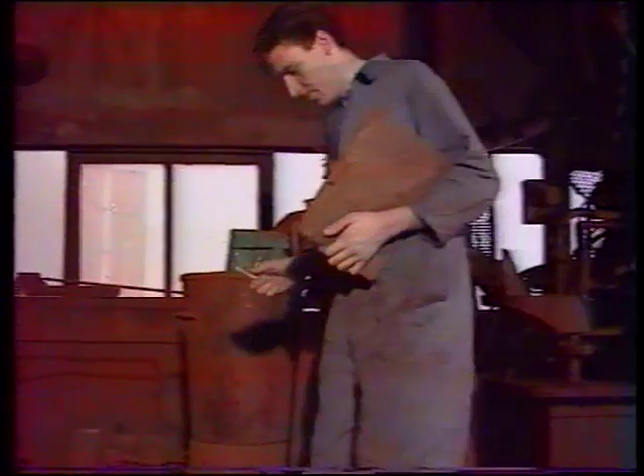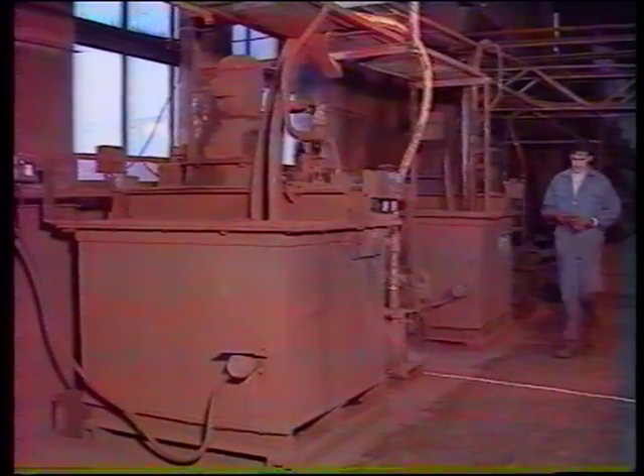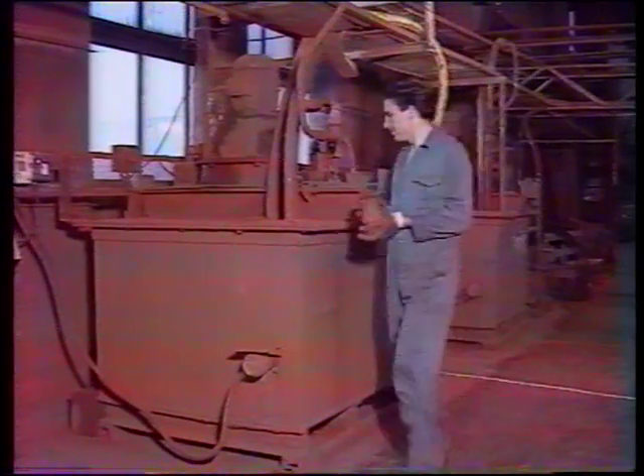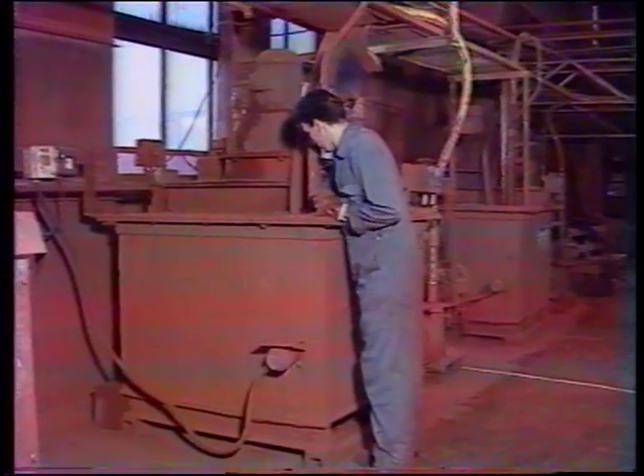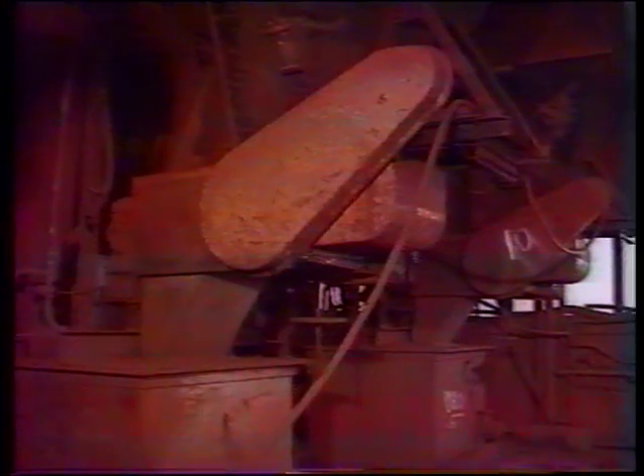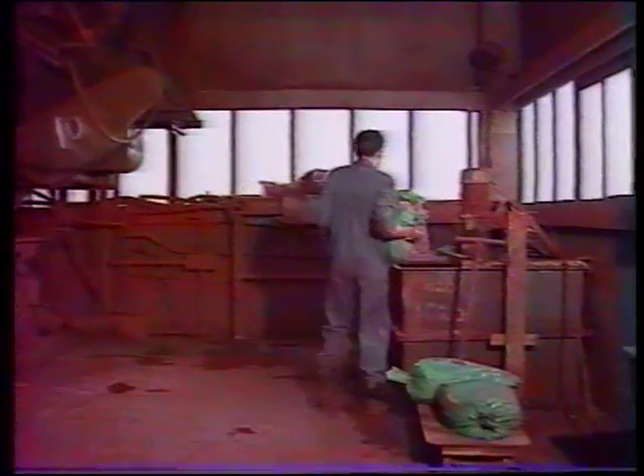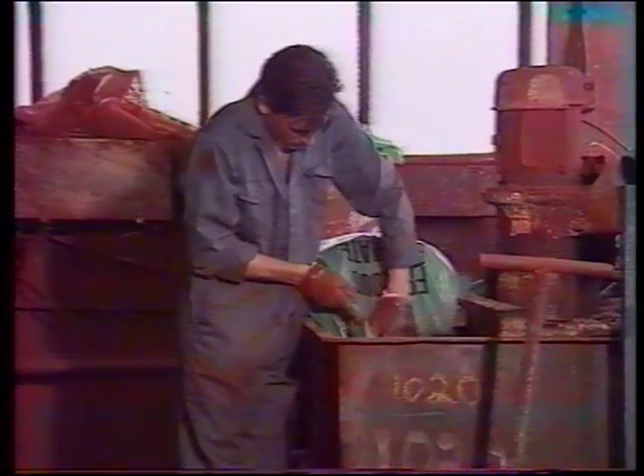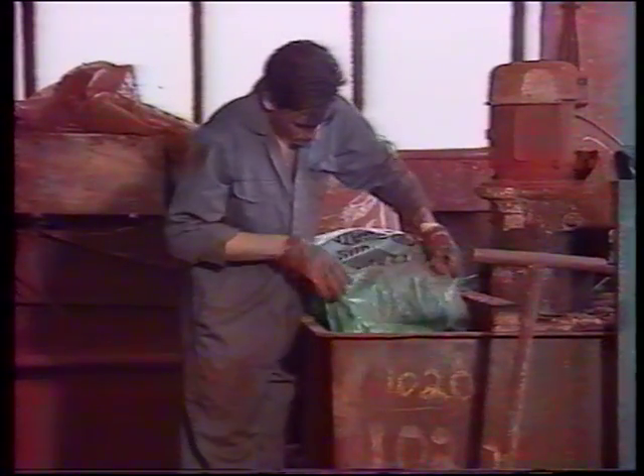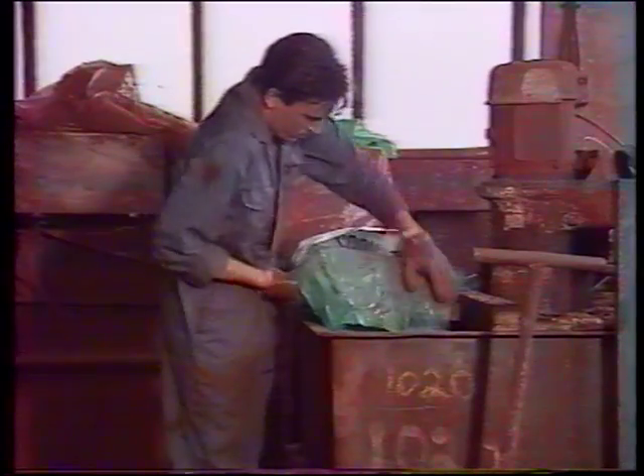The rouge mixture is prepared in a mixing plant at the side of the polishing line and is then fed onto the polishers through a ring main system. The tanks supplying this are located outside the mixing plant so the operators can maintain a careful check on their operation. The rouge mixing plant also incorporates thickening equipment to thicken rouge that has been through the polishers and has been recovered after passing through drains and cyclone equipment which removes coarser solids. This recovered rouge is mixed with fresh rouge to form the basic ingredient for the mixture that is fed back to the polishers.